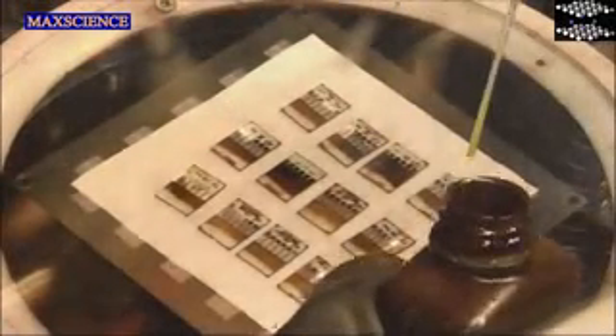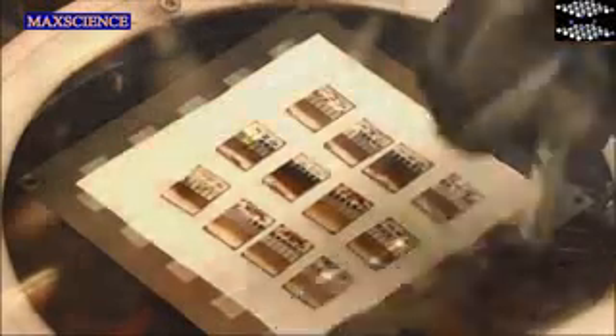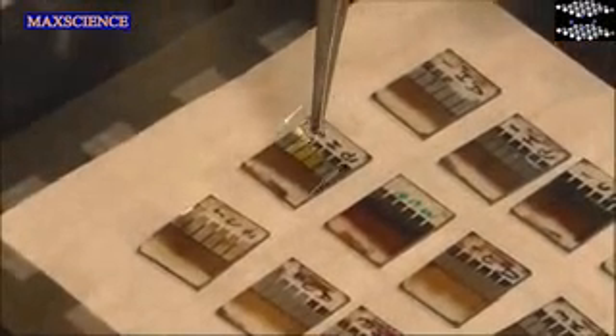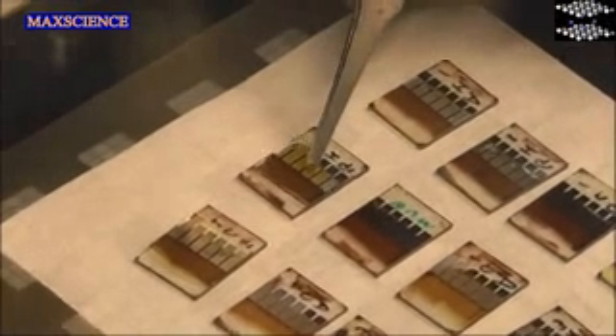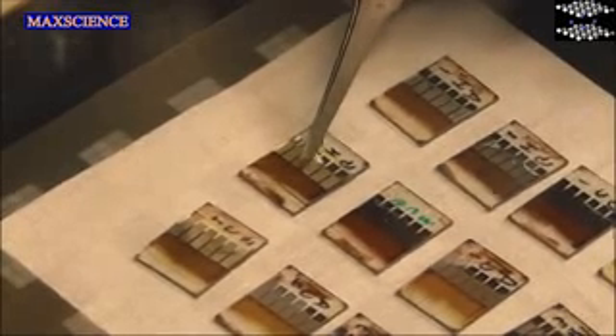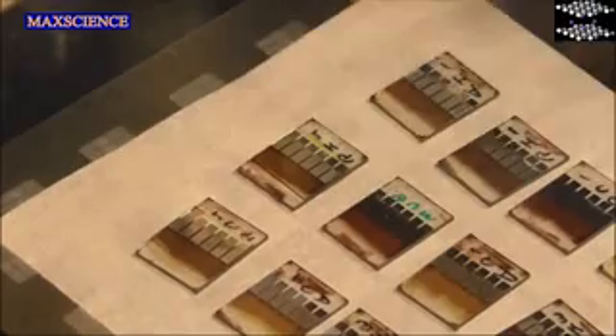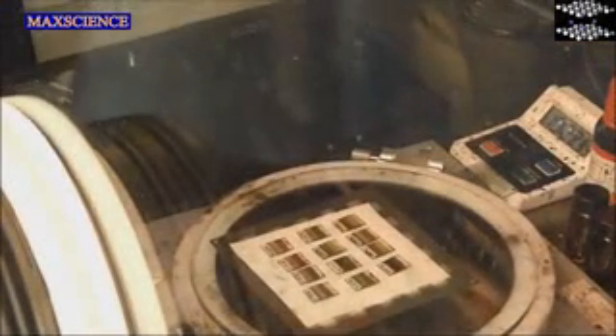Using a Pasteur pipette, drop a small quantity of UV curable epoxy on the center of the substrate. Place a glass cover slip on top of the substrate and press down to allow the epoxy to coat the device. Move the cover slip gently to help trapped air bubbles escape. Once all the cover slips have been placed in position, the substrates are ready to be placed under a UV lamp and cured for approximately 30 minutes. This encapsulates the devices and protects them from moisture and oxygen. The finished devices are now ready to be removed from the glove box.